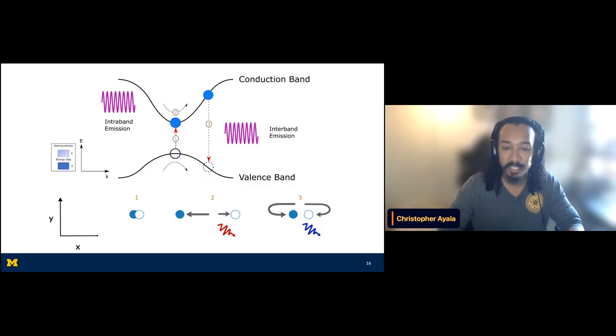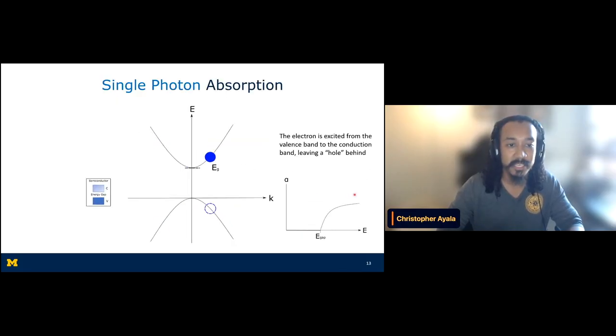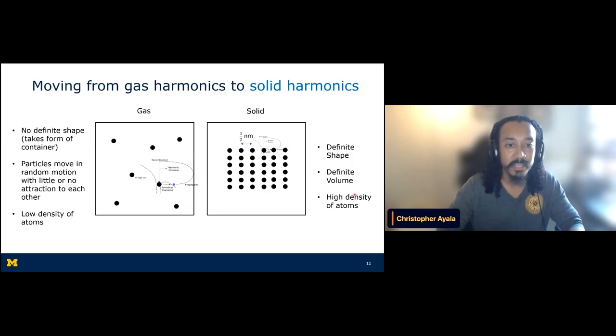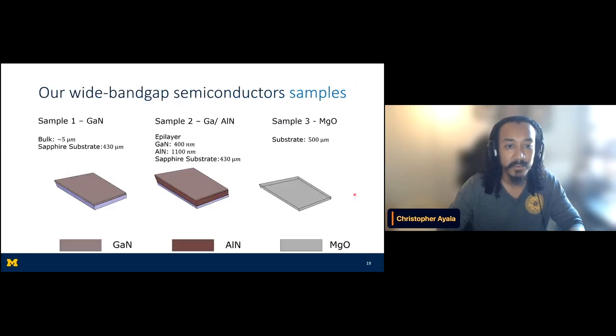But yes, the second material that I'm studying, specifically the gallium nitride. Oh, other way. Right here. So this material, as I was mentioning earlier, is grown via molecular beam epitaxy, in that you have the sapphire substrate, the aluminum nitride is grown right on top of it, and then specifically the gallium nitride is deposited across the material in a way that allows you to have, like I said, that fine material deposition. Okay, thanks so much.